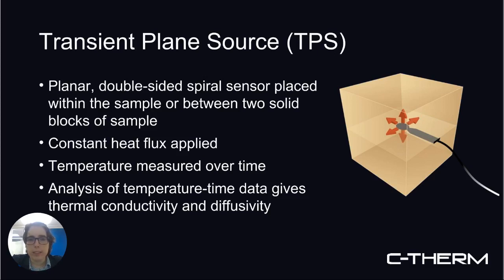So when you're running the test with the TPS sensor, you place the sensor probe in between two identical pieces of material. The data presented here uses the bulk algorithm, so the sample should be at least 5 times the sensor radius in diameter and at least twice the sensor radius in thickness in order to achieve a good test result. A constant heat flux is applied across the bifilar spiral heating element, and the temperature is measured as a function of time. The analysis of the shape of this temperature-time plot is what gives us the thermal conductivity and the diffusivity.